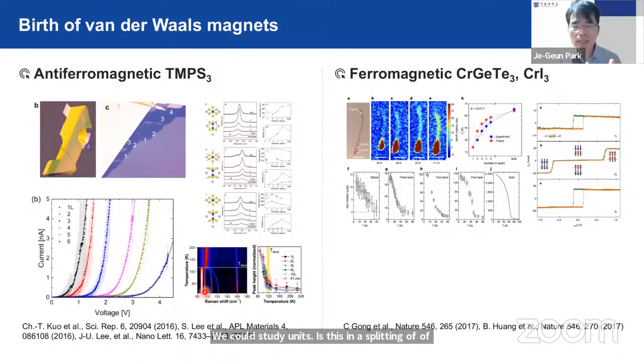And this splitting is basically measured as a parameter, and if you plot it as a function of temperature and thickness, then you see that even in monolayer, the splittings are there. So this is clear verification of the Onsager solution. And we also studied the other models, XY and Heisenberg, and published in these four papers.